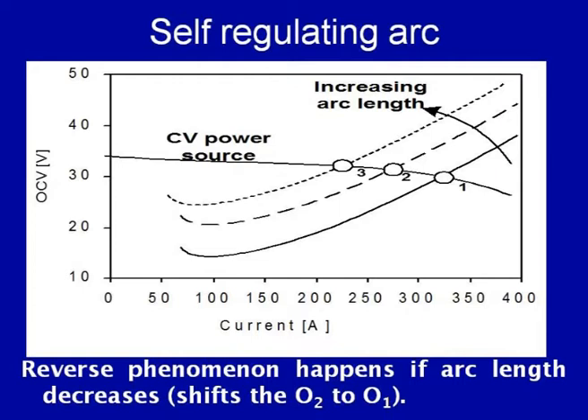So, for the constant feed drive system where a decrease in arc length has taken place, an increase in melting rate will result in the increased arc gap, and so helps in maintaining the arc length. That is how the self-regulating arc helps to maintain the arc length, especially when the constant voltage type of power source and the constant feed drive system are used. This principle is very frequently used for maintaining the arc length in the gas metal arc welding process and the submerged arc welding process, where small diameter electrodes are used.